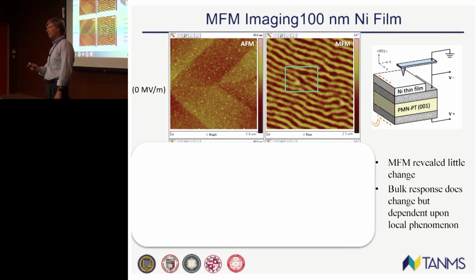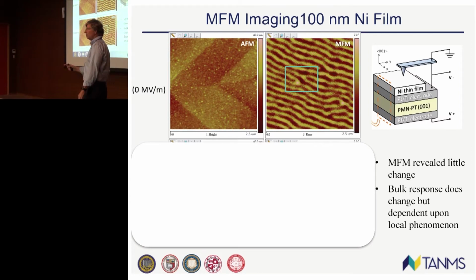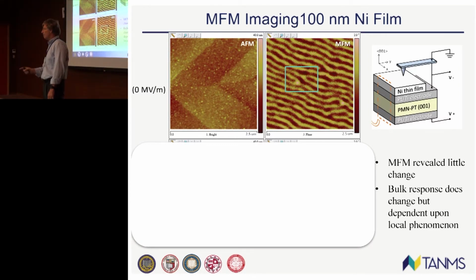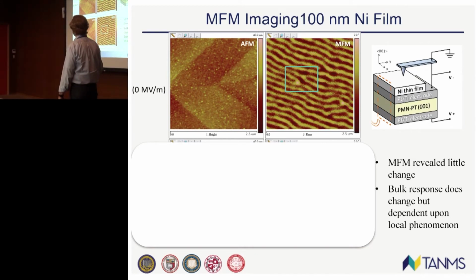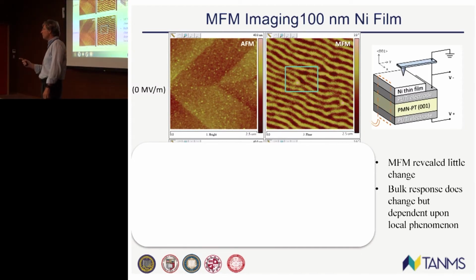But I want to leave you with an impression here. We got this wrong. And one of the reasons we got it wrong is we just tried to make stuff and test stuff. The one thing I've realized since working in this field is you really have to be guided by models. If you're not guided by some models or some predictive capability, you'll keep getting it wrong. So what we found here is you see this thickness? We chose too thick of a film. We were too far from that instability of closing that flux path off. What we later learned after we read papers is we should have chosen a thinner film.